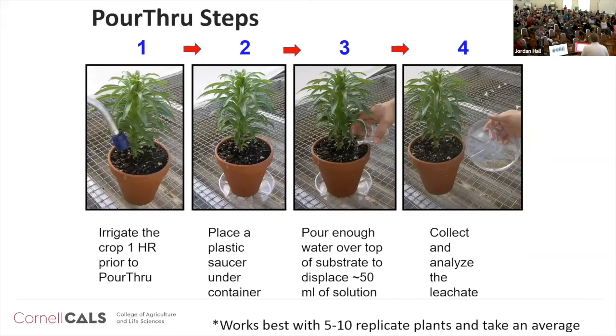So for the pour-through method, which is the easiest non-destructive method, you're going to water your plants about an hour before taking the measurement so that they can get to container capacity. You're then going to place a plastic saucer under the container. And then depending on the size of the container, you're going to pour a known amount of distilled water on top, and that's going to push out a leachate sample. So with a 6-inch pot, we're using about 50 milliliters of solution. And then you collect that leachate sample, and that's what you're putting your pH and your EC pens into.